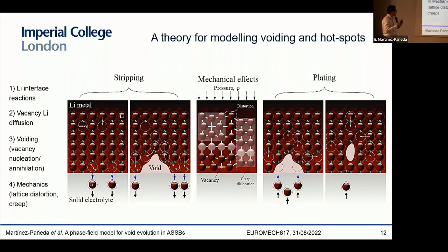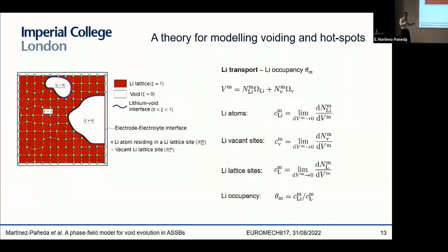And then last but not least are the mechanics effects. This is mostly lattice distortion due to the lithium transport, the vacancy diffusion, but more importantly, the creep effects that you get when you apply this constant mechanical pressure, this stack pressure on top of the board. So let me explain how we choose to model each of these phenomena. And for the sake of time, I'm only going to focus on the theory. I'm not going to get into the details of the numerical implementation, but I'll be happy to discuss those during the Q&A session. So let me tell you first what the primary fields are.